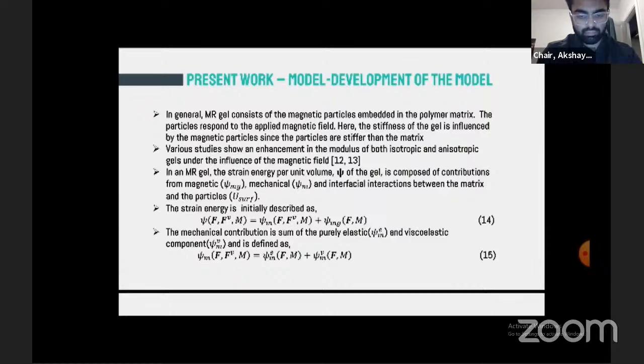The strain energy per unit volume of the gel is composed of the magnetic and mechanical contributions, and the term which we are introducing here is the interfacial interactions that occur between the matrix and the particles. First, I'll discuss the magnetic and the mechanical contributions. Later, I'll discuss the interfacial interactions. So, the strain energy can be described as the sum of the magnetic contribution and mechanical contribution. The mechanical contribution is further decomposed into two, which will be realized as a sum of the purely elastic one and the viscoelastic component.